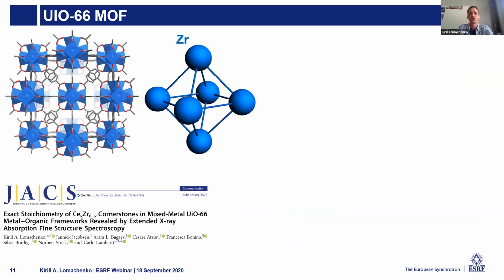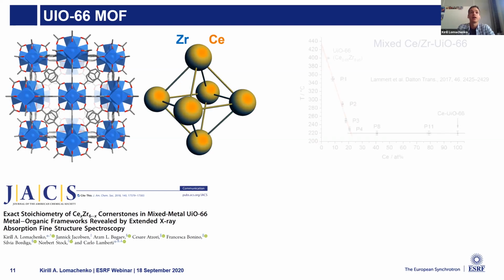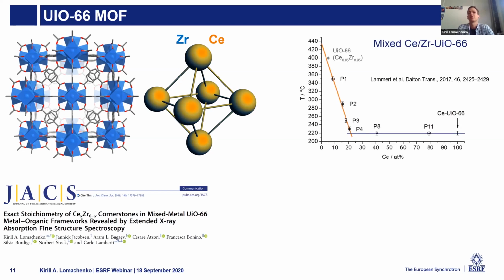But zirconium in these cornerstones can be partially or completely exchanged with cerium. A series of these materials with different cerium content was synthesized by a group of Professor Stock at the University of Kiel. What they saw is that the temperature stability of these materials, depending on the cerium content, is not very straightforward. So it was not really clear why it looks like this.